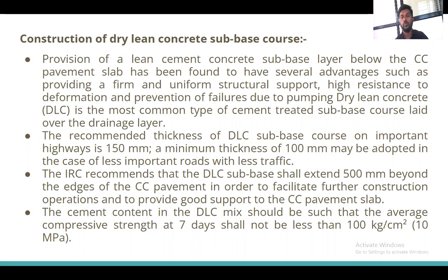The most common type of cement treated subbase course is laid over the drainage layer. The recommended thickness of the DLC subbase course on a highway is 150 mm, as we have seen in the video. If the road is of very low volume, then we have to maintain a minimum of 100 mm thickness. But generally, 150 mm thickness of the DLC is recommended.